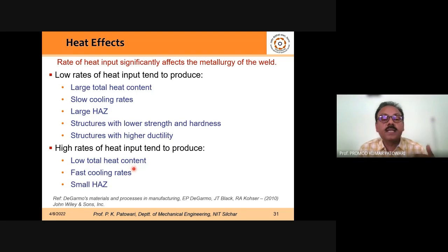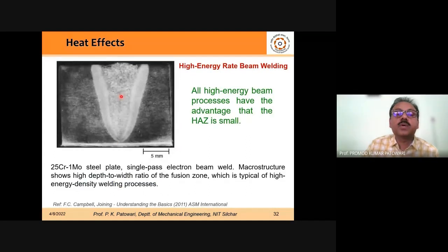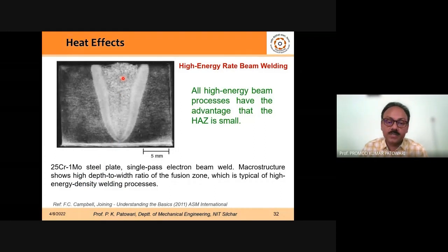And if it is so, then the energy will not get its chance to get dissipated inside the material or the nearby material. And if the heat doesn't go inside, then it's quite obvious that we are going to get a smaller heat affected zone. That is again one of the important issues. So now you see one example of a weld joint, and this is because of the high energy rate in beam welding. So here you can see the width to depth ratio. If you see, it is much deeper than wider.